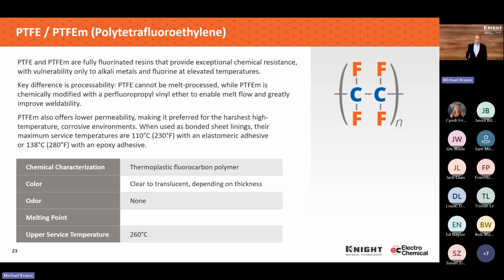So it has better permeation resistance than PTFE, which tends to have voids. And because it does flow a little bit, the weldability is better. So you can get better welds with it, which improve the quality of the parts. With both PTFE and modified PTFE, because it doesn't flow when you're actually doing welding, if you need a weld rod or cap strip, we're actually using PFA in there to weld to